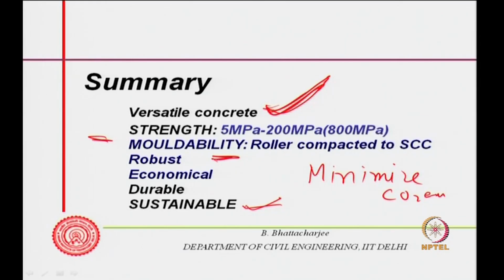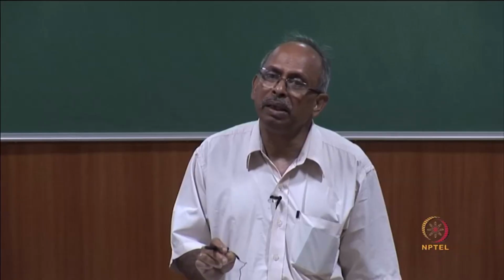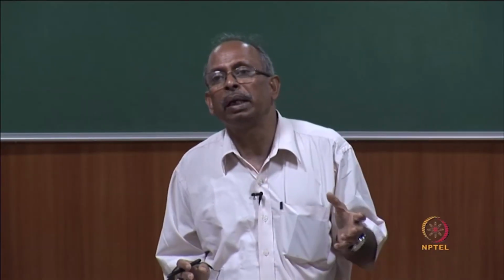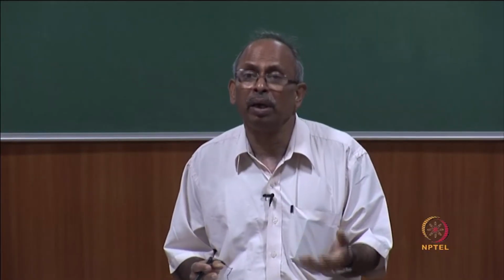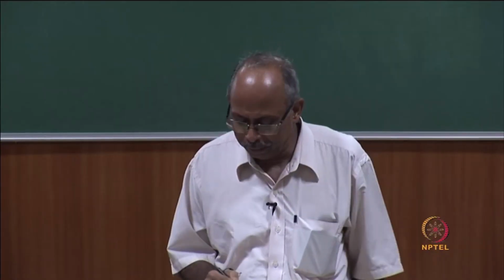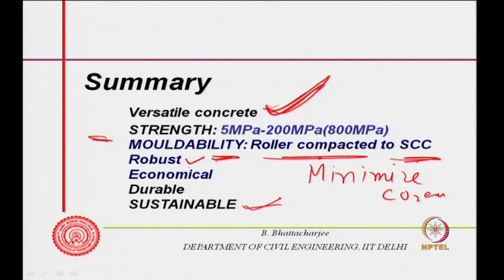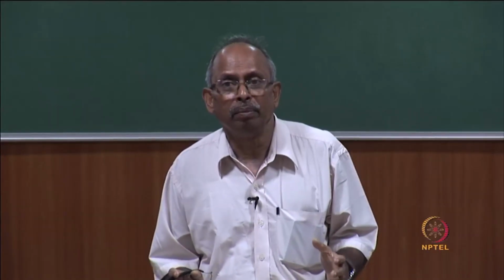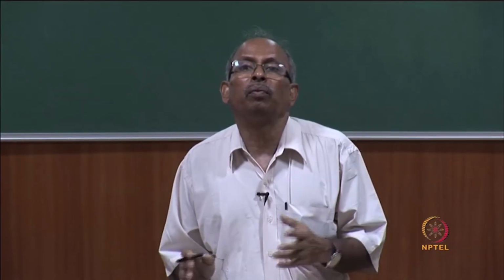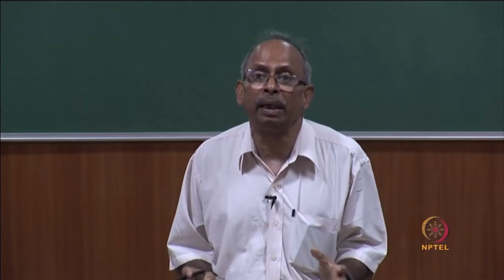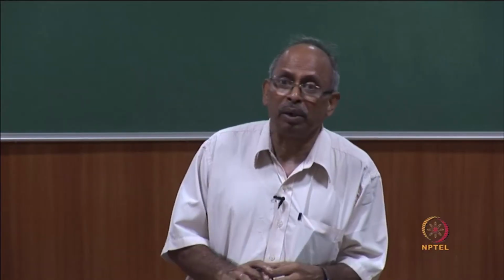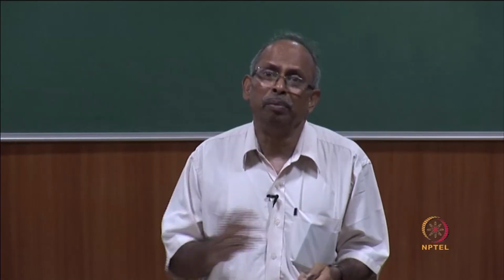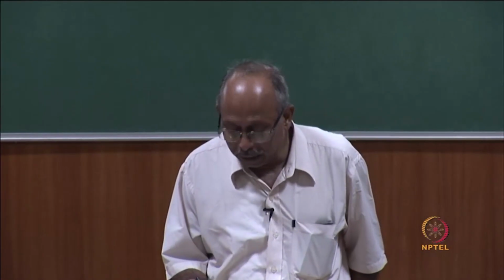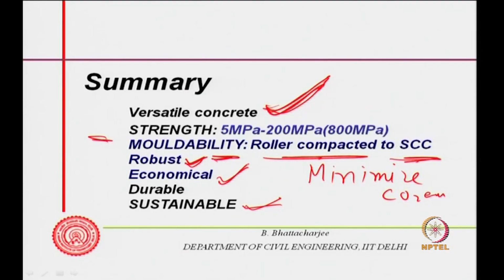If you look at moldability, roller compacted concrete, zero slump, to self compacting concrete, again it is versatile, a very high range. The tensile strength and ductility of course remain a problem for normal concrete, but then we do not use concrete as such in most of the cases. We use it as a composite, as reinforced concrete, or we pre-stress it, the way obviously providing reinforcement. It can provide robustness, massivity. A mass concrete dam, you can make it with concrete, or of course, in good old days it could have been masonry, but largely concrete provides that answer. You can't use most of the other materials. For example, you can't use a plastic polymer to really make a robust gravity dam, but concrete can provide you that. It is economical, it is cheap, and that is why it is used so much.